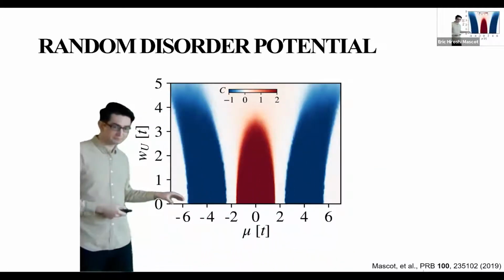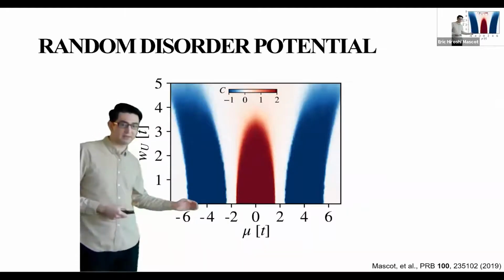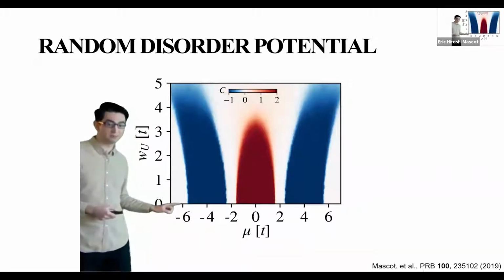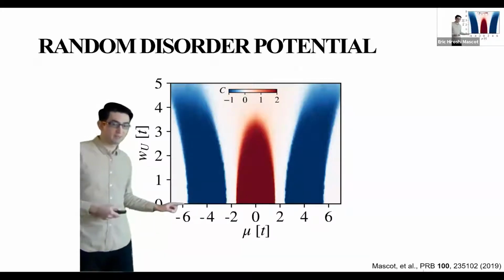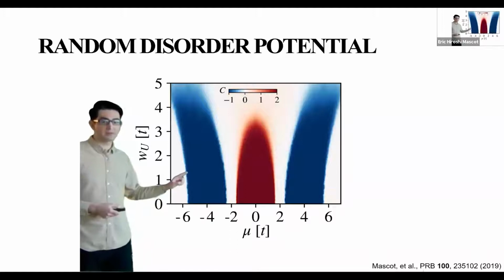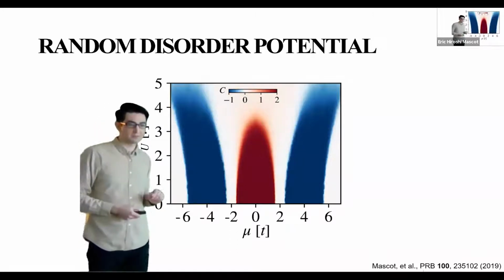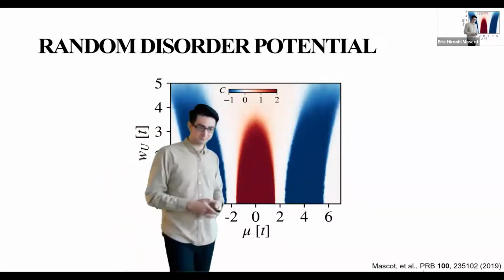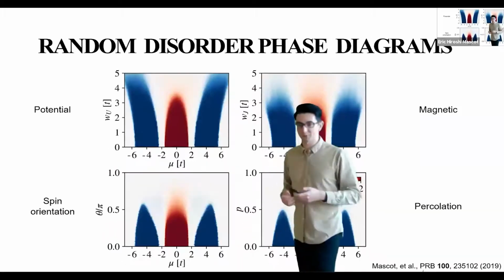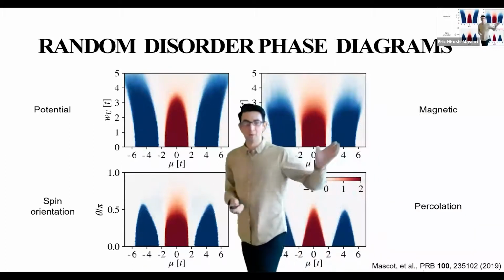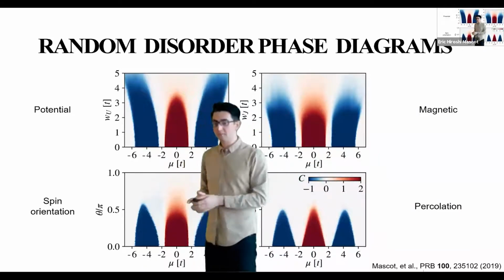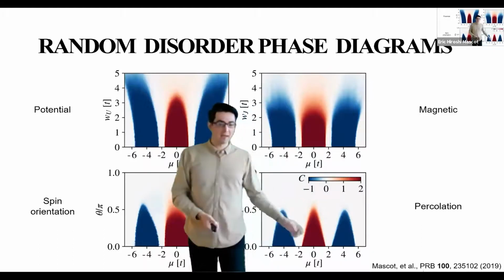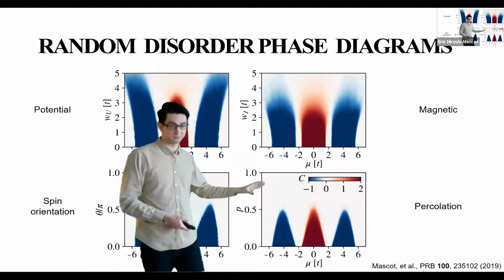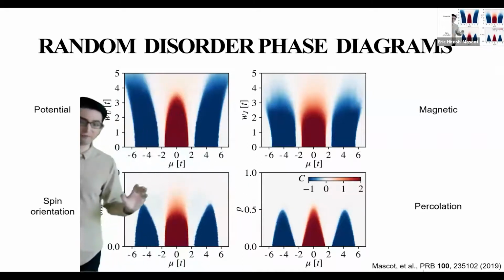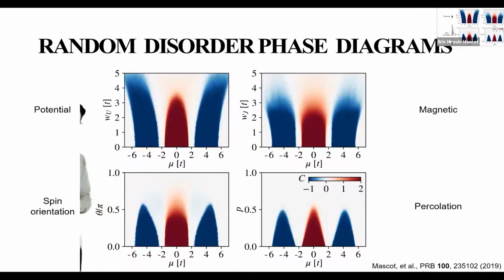And what's especially interesting is if we look over here towards the left of the phase diagram, here we have at the beginning where there's no disorder, it's in a trivial phase. But as we increase the disorder, we go into a topological phase. And so we can get order from disorder. And this wasn't the only type of disorder we looked at. That was the potential disorder. But we also looked at magnetic disorder, random spin orientations, and random percolation type disorder. And in all of these cases, we found very robust topological phases.